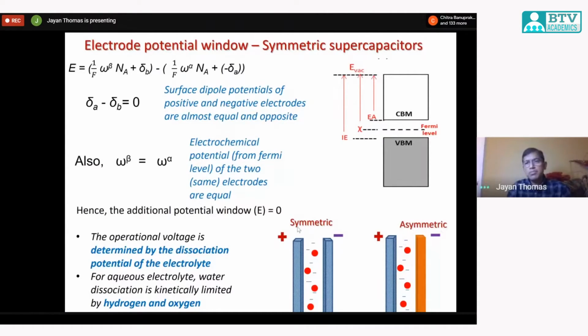For the symmetric one, you can see that the same material is used, so delta A minus delta B is equal to 0, as well as omega beta is equal to omega alpha. That is, the electrochemical potential of both the electrodes is the same in this case. So in this symmetric case, you are limited by the decomposition of your aqueous electrolyte, basically water. Your voltage is limited to about 1.24 volts, which is the decomposition potential of water. So you can see hydrogen and oxygen evolution in that case.